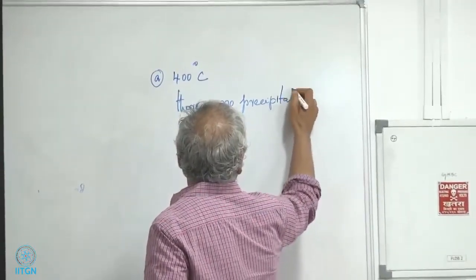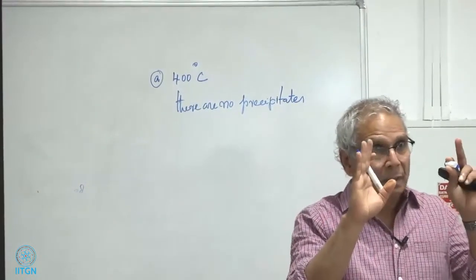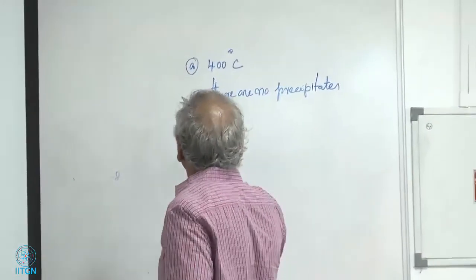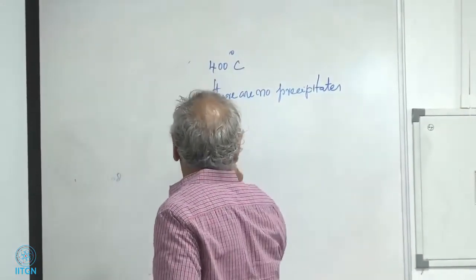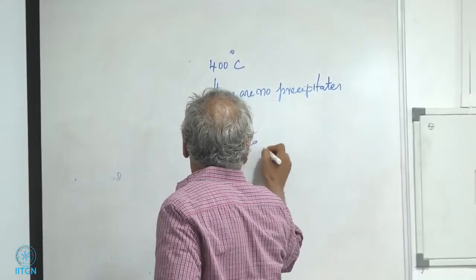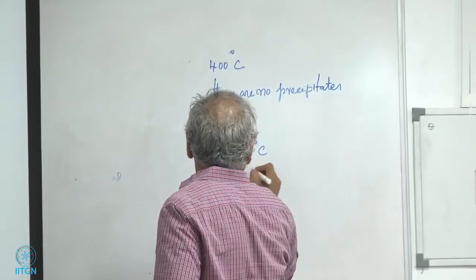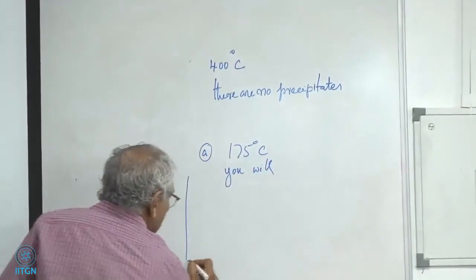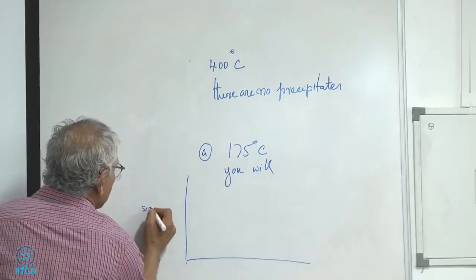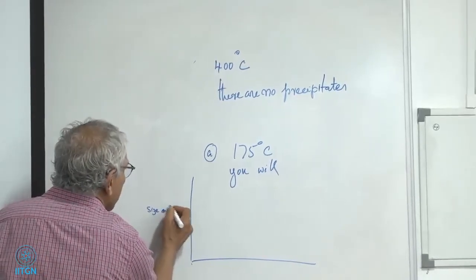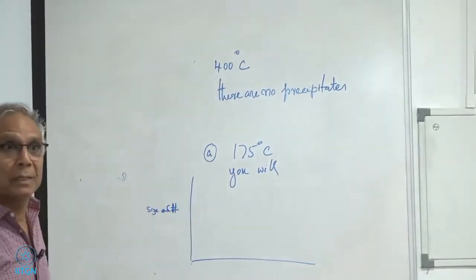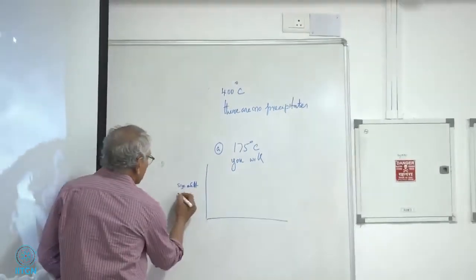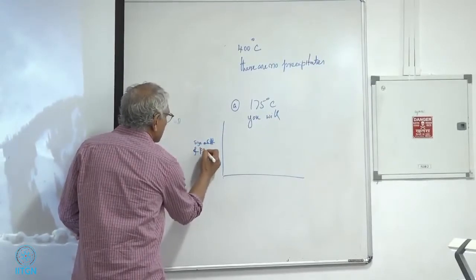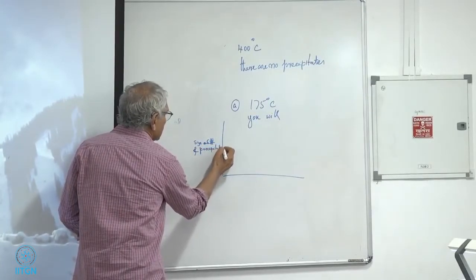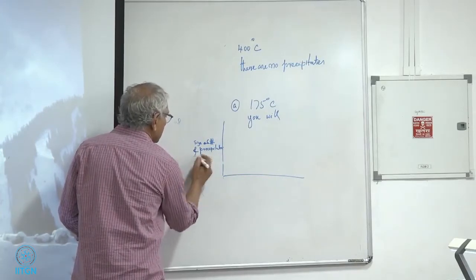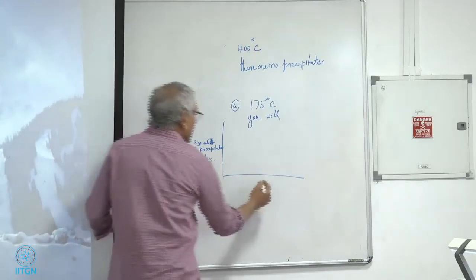There are no precipitates at 400 degrees C. Oh, you wanted the other way around. Okay, sorry. At 175 degrees C, you will nucleate. So basically, I think this is what you're asking: size and number of the precipitates, volume fraction, area fraction, at grain boundaries as a function of time.